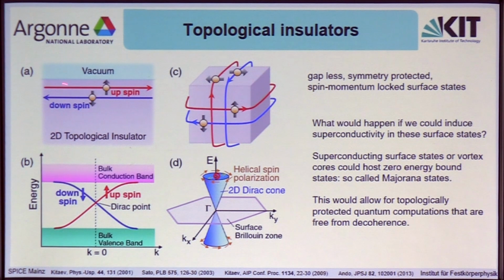Those surface states are symmetry protected, they are spin-momentum locked, and thus not very easily affected by scattering. Now, with the theoretical concept of a topological insulator also came the theoretical concept of a topological superconductor, which was very early on discussed for several one or two dimensional systems. And people realized that in these systems, due to the topological nature of the system itself, it's actually possible to have so-called Majorana states in either vortex cores or in the edge states of these systems that would also be symmetry protected and free from decoherence, and thus have the possibility to allow for quantum computing.